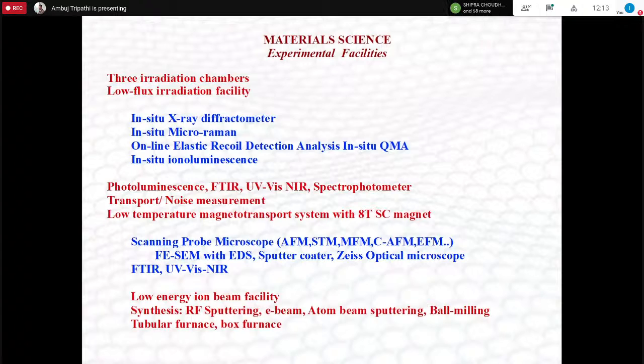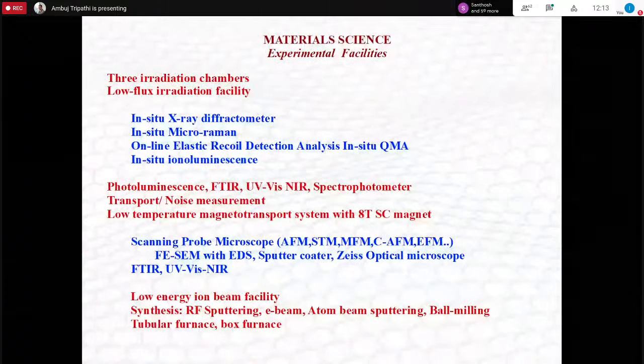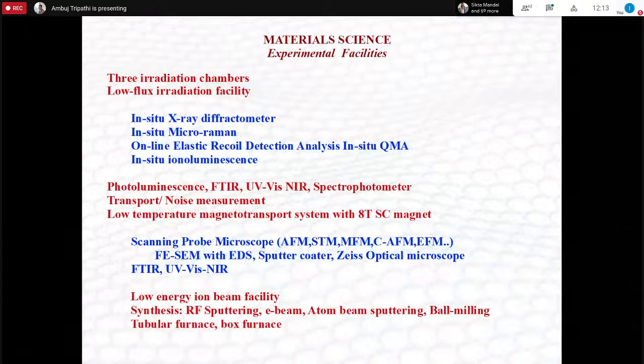Besides this pelletron and higher energy, we also have some very low energy facilities for low energy irradiation. We have two facilities. I will show those in the next slide. And for doing any of these things, you need basic sample preparation techniques. So we have an electron beam evaporation system, RF sputtering, and atom beam sputtering. And for going into all that, what you need is ball milling and furnaces, a box furnace and a tubular furnace, and all that is there.